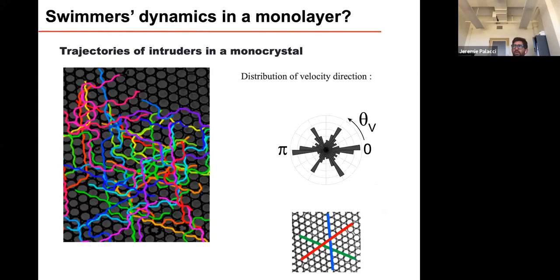So in order to do that, we step back and we look at the microscopic properties of our system and what were the effects of the swimmers in the monolayer. If you look at the trajectories of the swimmer in the monolayer, what you see is that they tend to follow the direction of the crystal. And so we see that they, on average, only follow those directions. Okay, and that's what you can see in the trajectory.